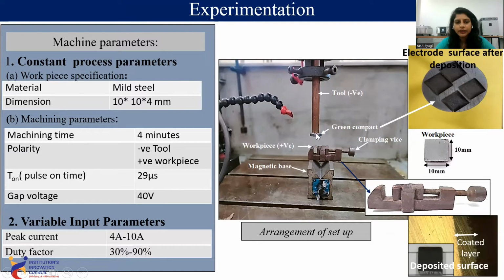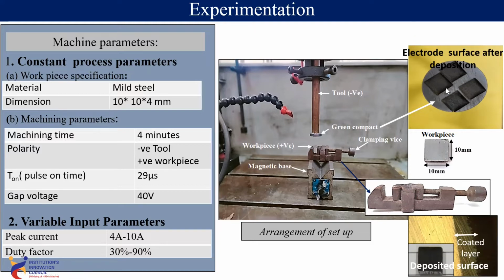These parameters were decided by performing trial experiments. In the arrangement of the setup, the green compact tool is held in this tool holder, and this is the magnetic base which is attached to the clamping vise. In the clamping vise we have attached the workpiece. This is the setup that we are utilizing. After the coating, it is observed that there are holes in the electrode surface after deposition, and there is a deposited layer that we have obtained.